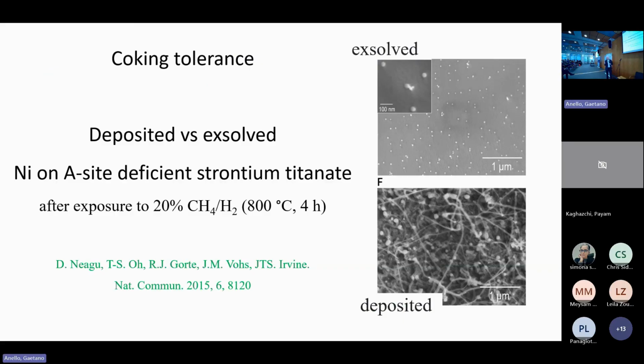Now, one of the key things about these pitted particles is that here you have deposited nickel, and here you have exsolved nickel. These have been in 20% methane at 800, and you get lots of nanofibers and a totally destroyed electrode in this system. But with the exsolved particles, there's very little carbon deposition, and what there is is basal growth. So you maintain your electrode structure.